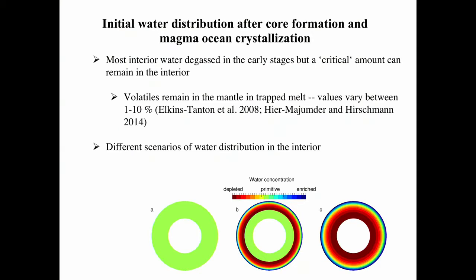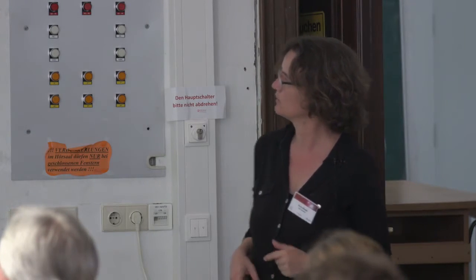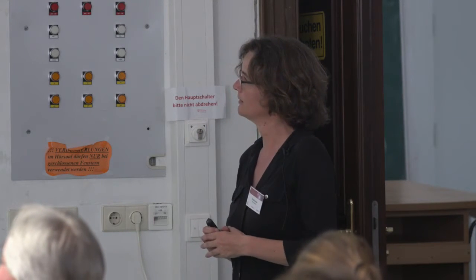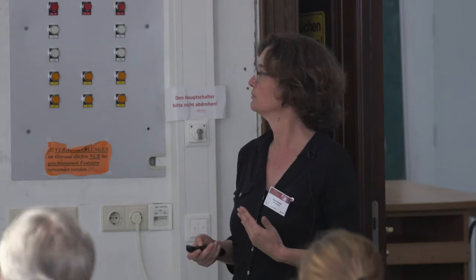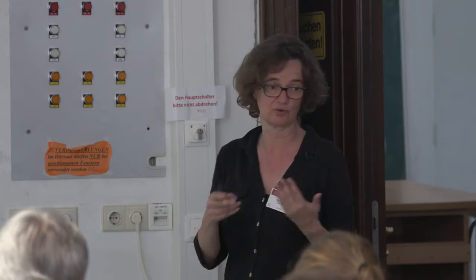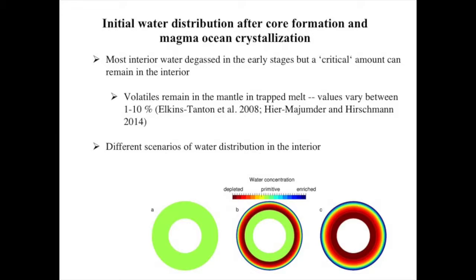But again, from the overturn and all these processes, the question now is, how is the water distributed? If you remember, it can be closer to the surface, but during continuous convection it can also be mixed, more homogeneous. That is an open issue, how that melt and that water is distributed. And typically people assume a homogeneous distribution of volatiles, but I think the next step would be to look into more detail at where the water-rich material really is in the interior of the planets. For instance, for Mars, as I mentioned, the lower mantle in principle can store a lot of volatiles in comparison to Earth, where we have this small transition zone where you can store more water. And that can also strongly influence the dynamics of the interior.